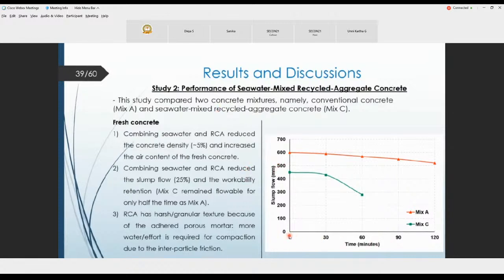Looking at the result of the slump flow, combining seawater and RCA reduced the concrete density about 5% and increased the air content of the fresh concrete. Combining seawater and RCA reduced the slump flow by about 25%, and the workability of mix C remained flowable for only half the time as mix A.